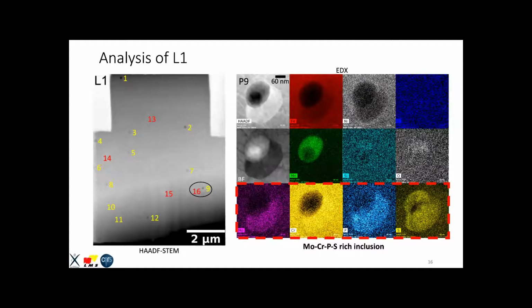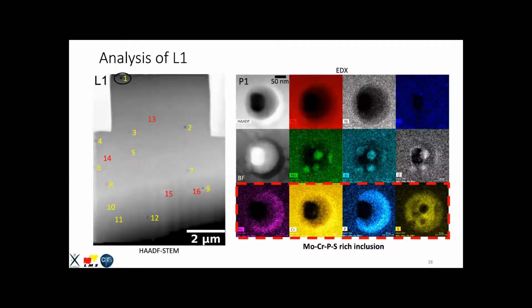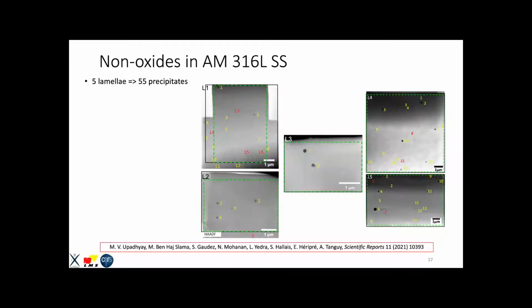only manganese silicon oxides. We look at the second precipitate, the exact same thing. There is a molybdenum, chromium, phosphorus-rich, sulfur-rich inclusion. Okay, at this point, we considered the possibility that there can be non-oxides present in additively manufactured 316L stainless steel. To prove that or to disprove that, we looked at all the 5 lamellae and identified 55 precipitates in them.